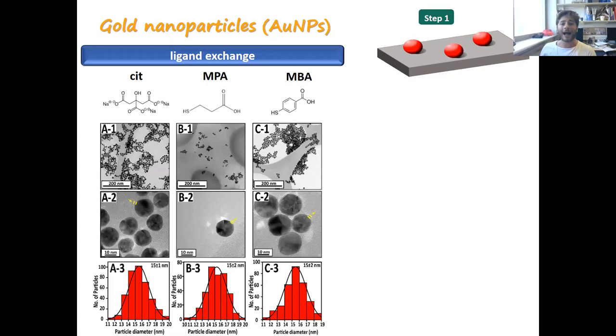In my project, I synthesized three different gold nanoparticles stabilized with citrate, with mercaptopropionic acid, and with mercaptobenzoic acid. These gold nanoparticles have relatively subtle changes in the functional group, and we want to study the effect of these minor changes on the supramolecular interaction between the matrix and the particles, and more specifically to study the recognition ability of our system. All particles are 15 ± 2 nanometers. We succeeded in synthesizing uniform, narrow-size distributions, and all nanoparticles are spherical. We synthesized these nanoparticles by a ligand exchange method to bestow them with different ligand shells.